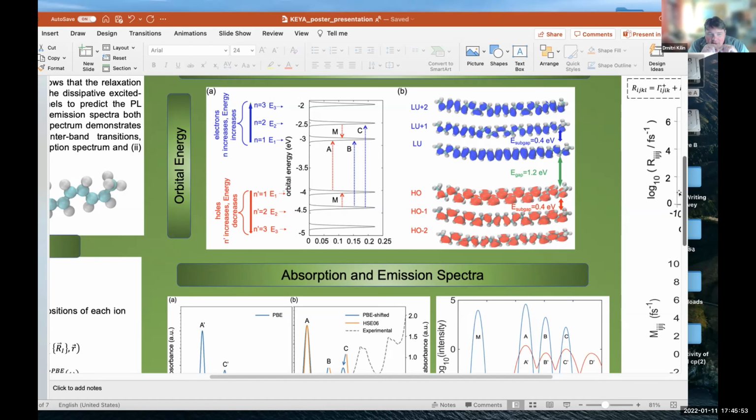So the material that Kia is considering is a conjugated polymer made of carbons, but due to specific bonds of order 1.5, it conducts electricity the same as metal. And we have a strand of limited length, like a stick with a beginning and an end. Inside, the electron can move freely, and outside it is forbidden.